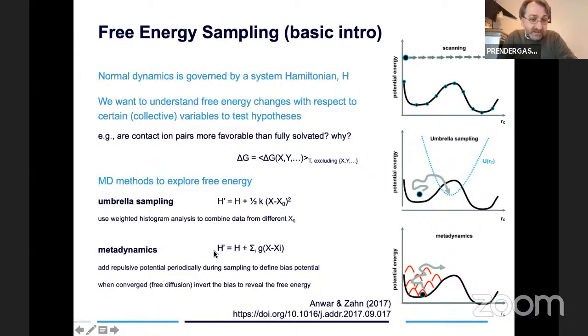There's also metadynamics, which is an ingenious approach developed by Michele Parrinello, where you leave, and Alessandro Laio, sorry, you leave behind kind of little breadcrumbs to remember where you have been that prevent you from revisiting that region of free energy space again and again. And so that helps you very much to climb out of local minima in the free energy landscape and to explore new minima. And so we've made a lot of use of these two techniques, and particularly metadynamics, for long simulations using classical molecular dynamics.